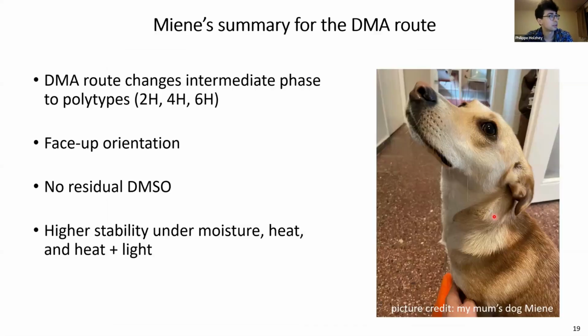So yeah, I have a little summary. So the DMA route changes the intermediate phase to polytypes. And then only after annealing, we go to the perovskite phase, which is face-up oriented. There's no residual DMSO, and it has higher stability under moisture, heat and light. So really all factors.